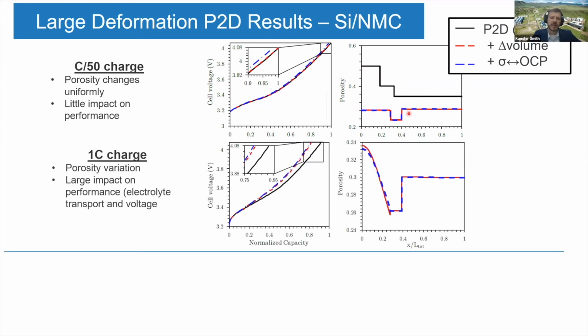At the 1C charge rate, you start to see a bit of separation between these different cases. So here, another interesting thing is that the silicon anode has a non-uniform porosity. There's a gradient. The smallest porosity is close to the front of the current collector because the electrode gets used preferentially at that region. And that shuts off electrolyte transport at that region. And so with the volume expansion, you see different behavior. You also see a little bit of dependence of the open circuit potential on hydrostatic stress, and that's the difference between these blue and red lines, but it's really pretty minor.